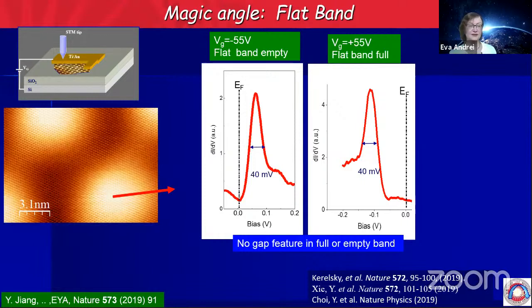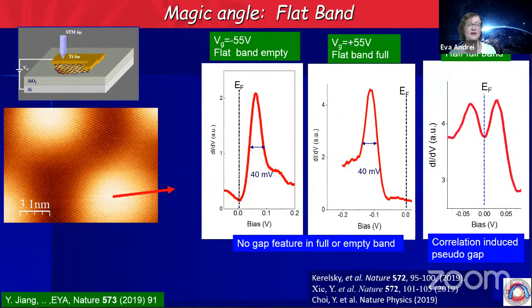So as a result, we park our Fermi energy way below the flat band, and this is what it looks like. We see the flat band appearing here. The width is about 40 millivolts. Then we park the Fermi energy way above the flat band, so we fill the band. Again, it looks the same. And now we can walk our Fermi energy and put it inside the band to see whether we get a correlated state and what it would look like.